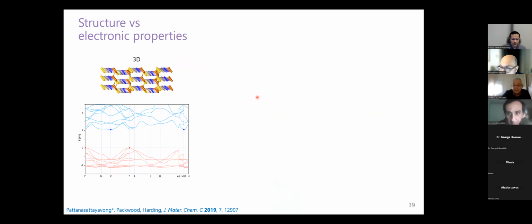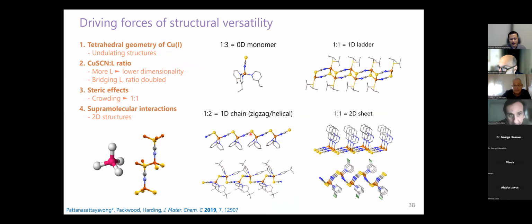So by modifying the copper thiocyanate, essentially intentionally adding some ligands to the copper thiocyanate. When the ligands coordinate with the copper, they can actually generate different topologies or different dimensionalities of the structures. In this case, for example, using just pyridine, if we can control the ratio between the thiocyanate and the pyridine ligand to be 1-to-1, it would form into a 2-dimensional sheet of the copper thiocyanate. Okay. So the parent structure is like this.